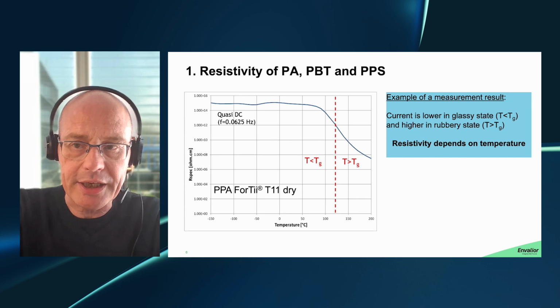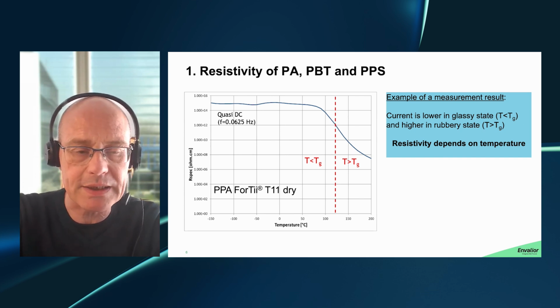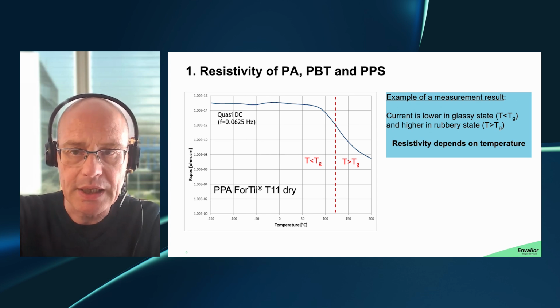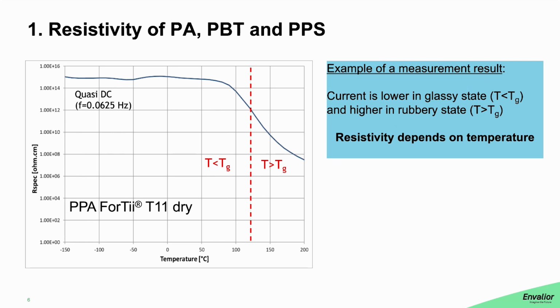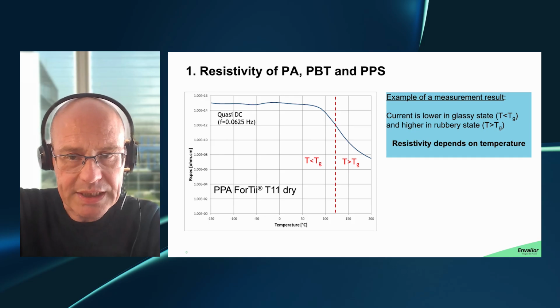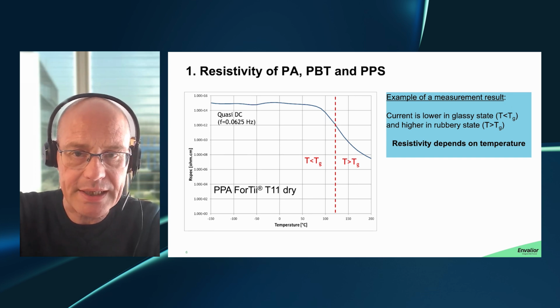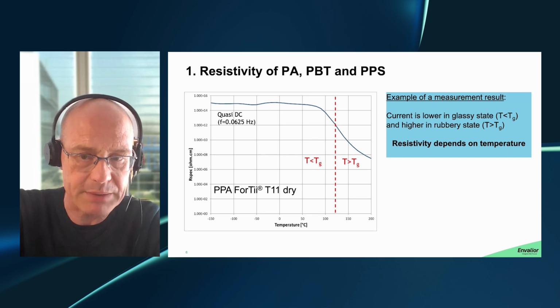That is displayed here in a typical measurement for polyamide 4T, a PPA, aromatic polyamide. So what you see depicted here is the resistivity of the polymer as a function of the temperature at which you do the measurement. And what is indicated in that red vertical line is the glass transition temperature. So what you see is that at temperatures lower than the glass transition temperature, you have a high resistance, low current because of the glassy response. The charge carriers cannot easily move through the material, and at higher temperatures above the glass transition temperature, you see a drop in resistivity because now the charge carriers can move through the material more easily. All this simply to illustrate that resistivity is indeed a function of temperature for these polymers.